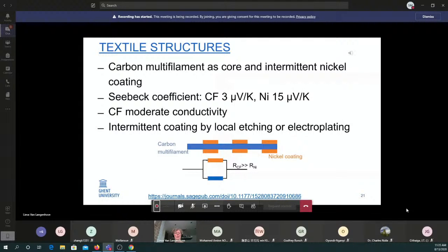The textile structure, we have used carbon multifilament as a conductive core and nickel as the second material. The Seebeck coefficients of the materials are 3, and they should be -15. So we can expect a theoretical output voltage of around 18. And the carbon fiber has a moderate conductivity, which is needed to make sure the current is passing through the nickel coating in the dedicated area. And this allows to create such a thermoelectric effect by using a textile yarn inserted by a regular weaving process.